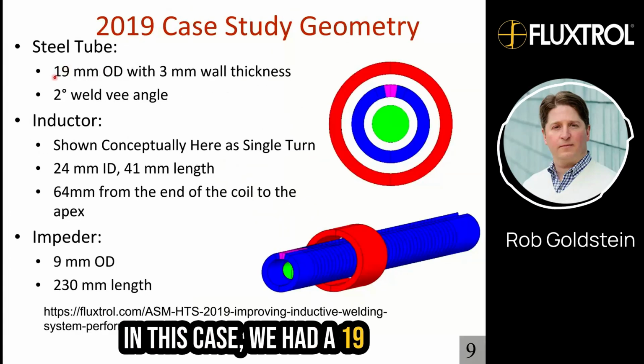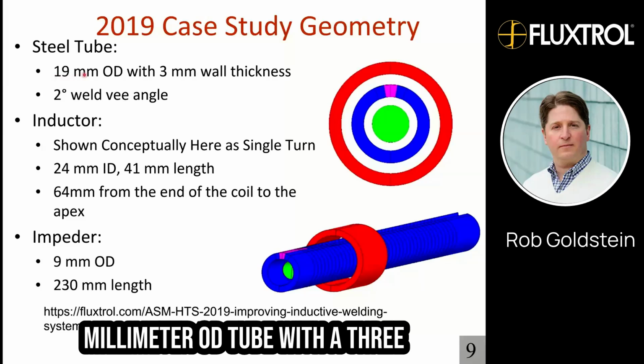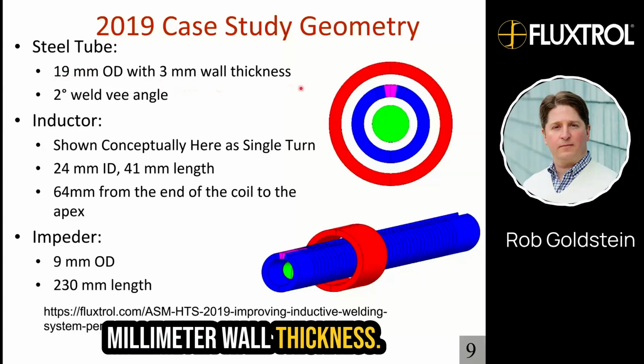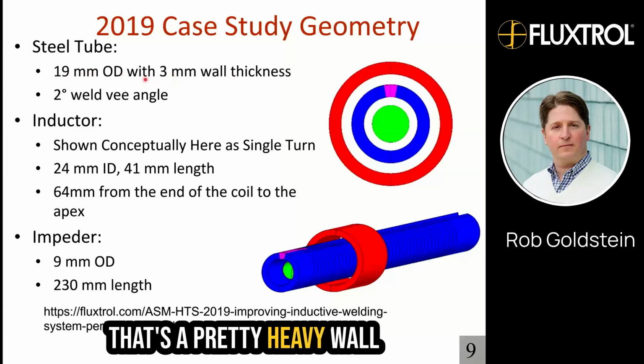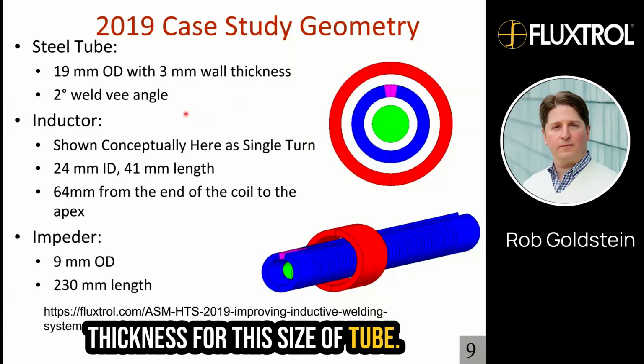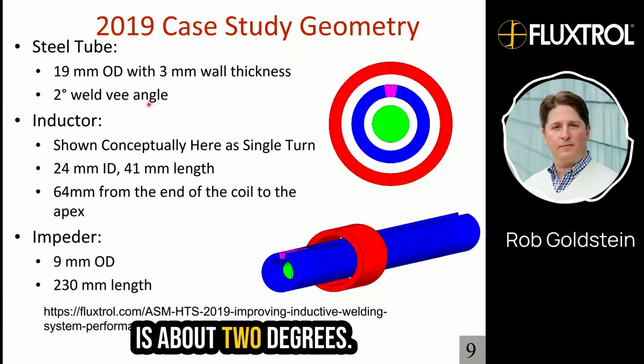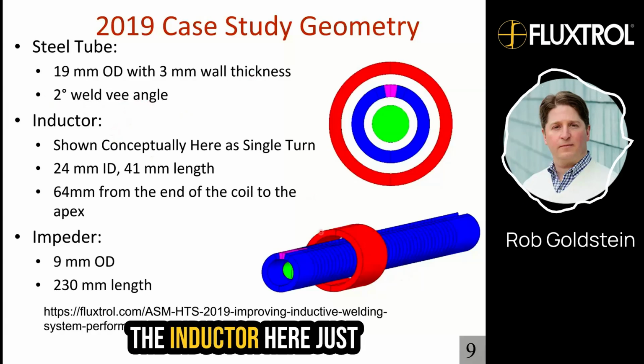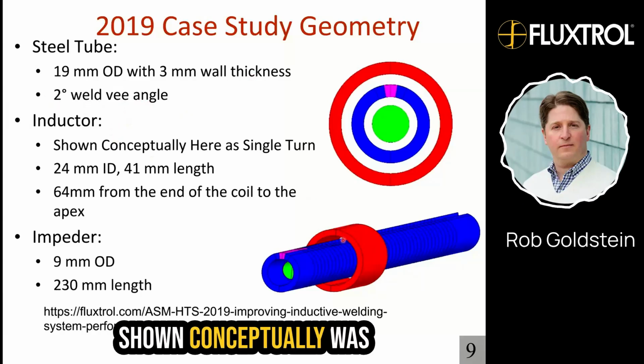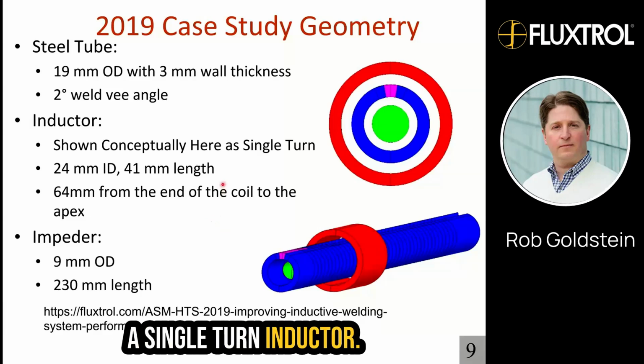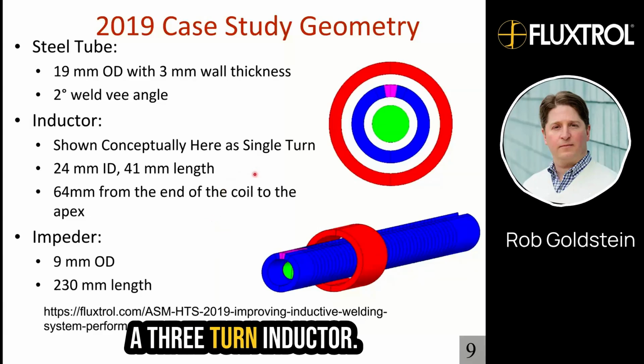In this case, we had a 19 millimeter OD tube with a 3 millimeter wall thickness. That's a pretty heavy wall thickness for this size of tube. And the weld V angle was about 2 degrees. The inductor here just shown conceptually was a single turn inductor. In reality, I believe it was a 3-turn inductor.